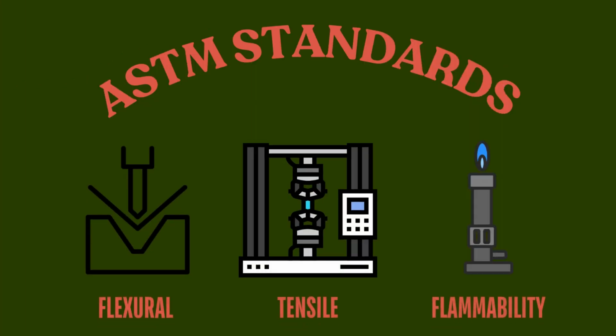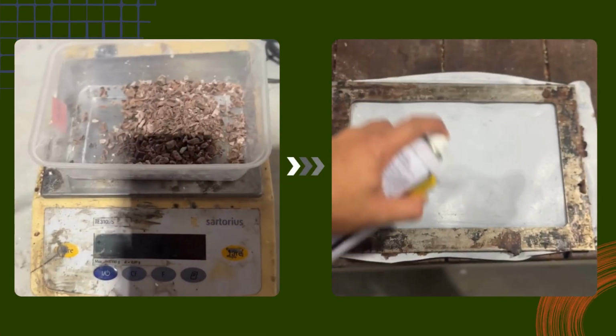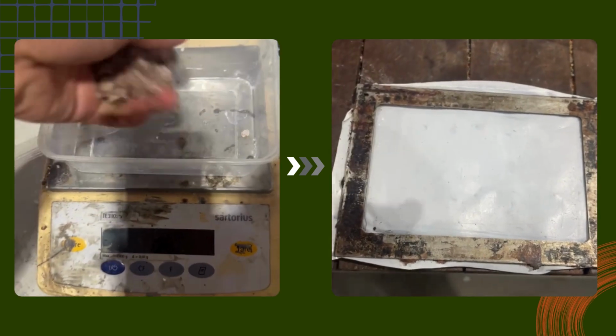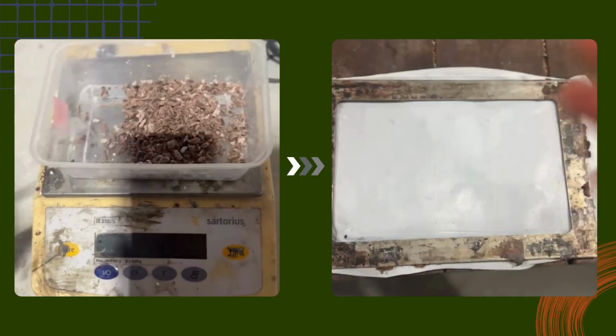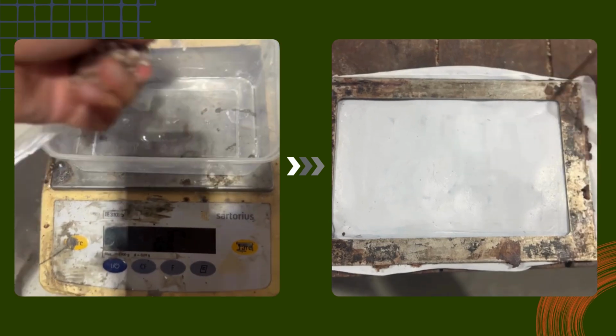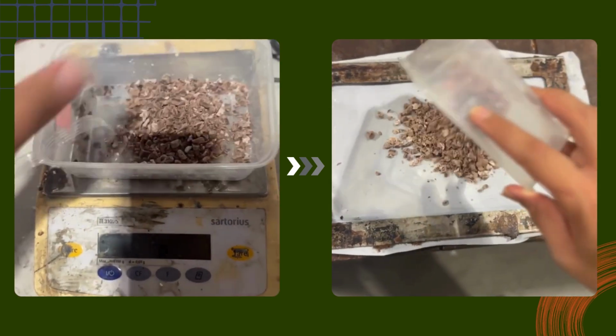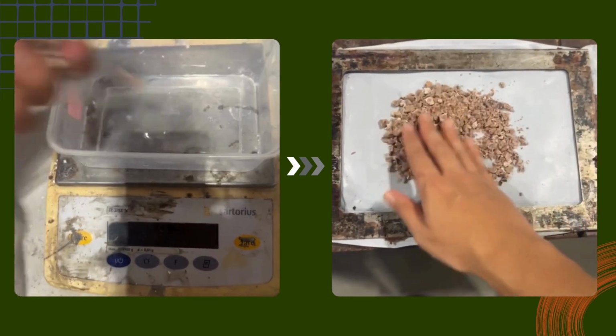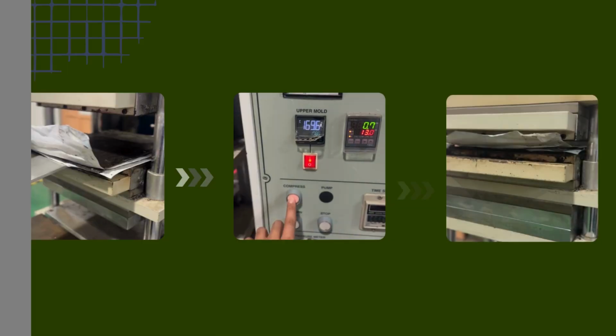We don't stop at just creating the material. Our composite samples are molded according to ASTM guidelines and rigorously tested for tensile and flexural strength and fire resistance. We began by accurately weighing the crushed samples to ensure proper proportions for testing. First, we sprayed mold release onto the mold surfaces to ensure easy separation of the samples after processing. Next, the weighed samples were evenly spread onto a specific ASTM mold. The mold was then placed onto the heating element of the hot press, where it was compressed under high temperature to facilitate melting and proper flow of the material.